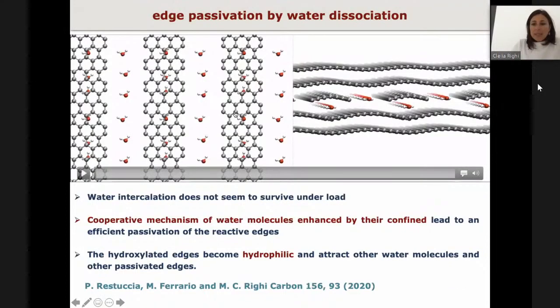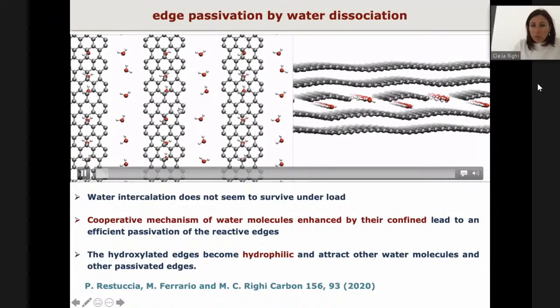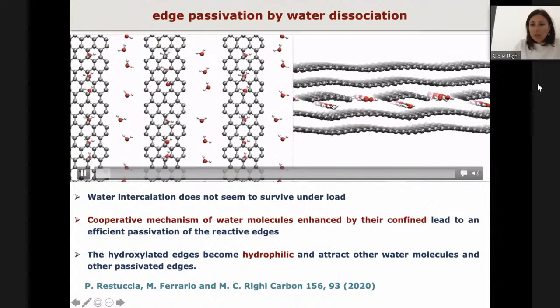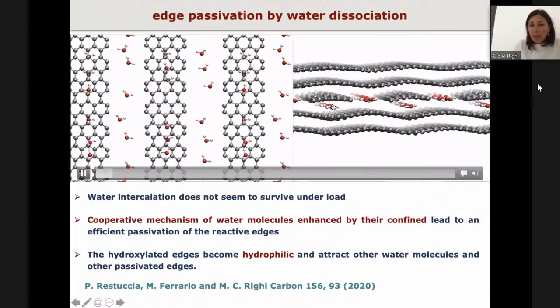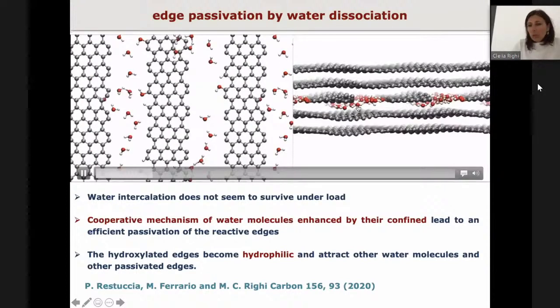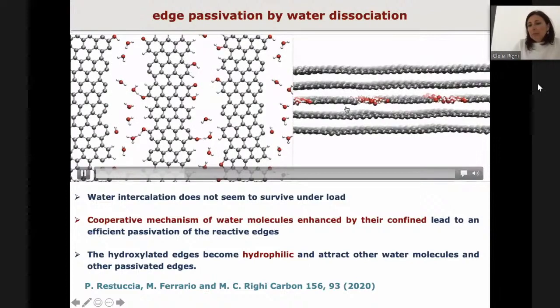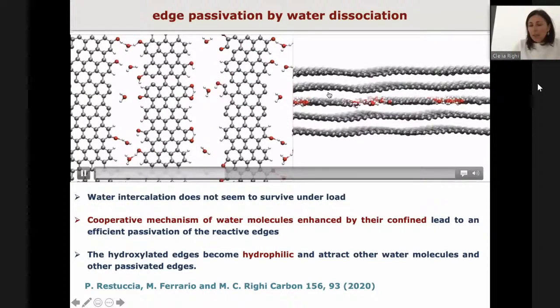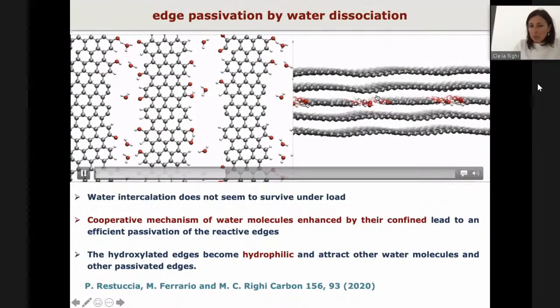You can see here the atom trajectories during the simulation from a lateral view and a top view here on the left of the quantum region. First of all, you can notice that the water molecules escape from the intercalated region. And this rules out a proposed hypothesis on the effect of humidity on the lubricating properties of graphite.